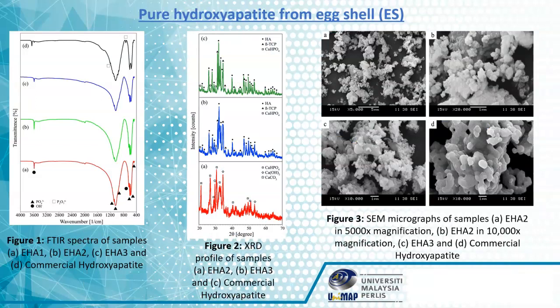For the results obtained, firstly, for the FTIR spectra, all of the hydroxyapatite produced from the eggshell waste show very similar spectra with the commercial hydroxyapatite. This indicated that the produced hydroxyapatite from eggshell waste was very pure as compared to the commercial hydroxyapatite. This is also the same for the XRD profile, which all of the hydroxyapatite samples produced from the eggshell waste show the same profile as the commercial hydroxyapatite. And lastly, for the SEM micrographs, the morphology or the shape show very similar or identical shape with the commercial hydroxyapatite, which is very good to be used as artificial bone application.